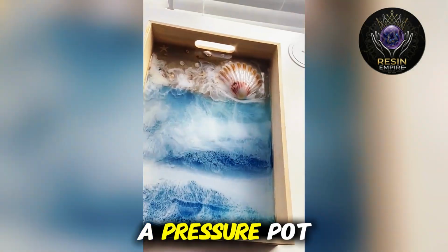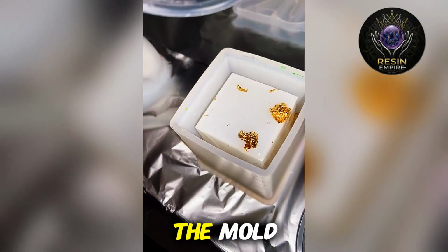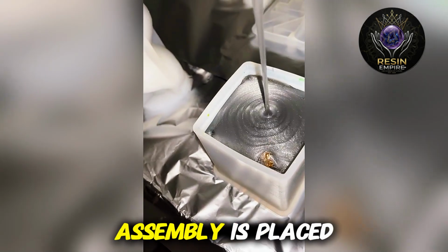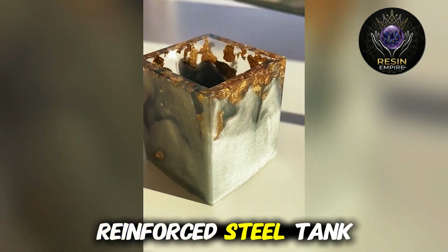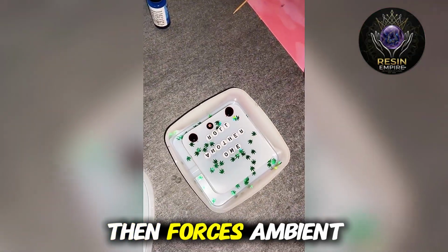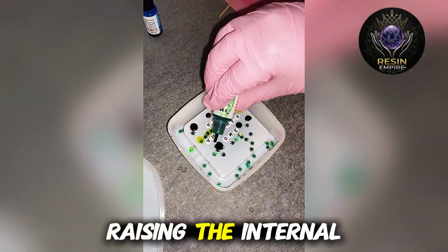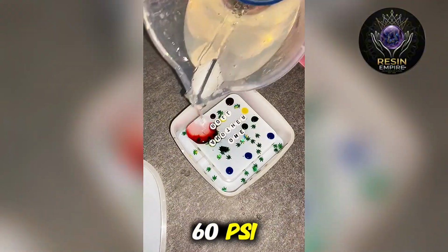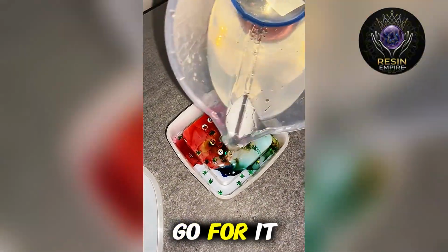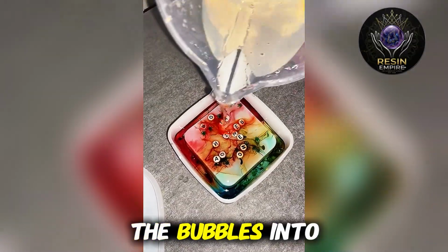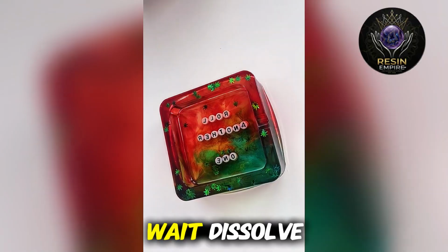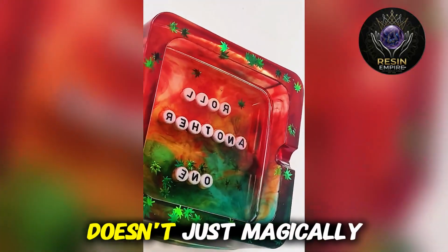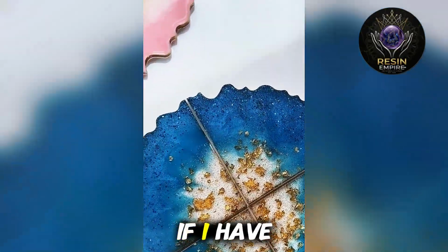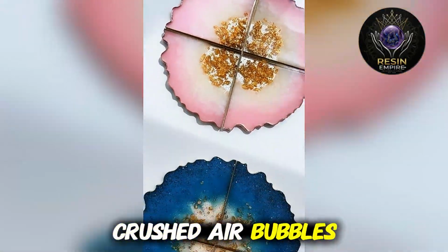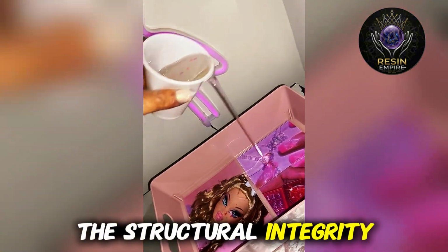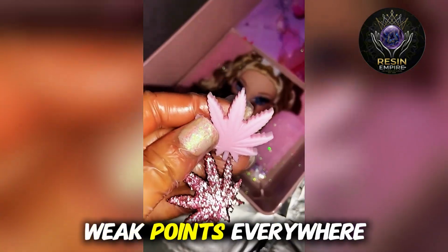Precisely opposite, yes. A pressure pot is utilized after the resin is poured into the mold. Okay, so the mold goes in. The entire mold assembly is placed inside a heavy-duty reinforced steel tank. An industrial air compressor then forces ambient air into the sealed tank, raising the internal atmospheric pressure to around 50 or 60 psi. And this is where I need to challenge the physics a bit. Go for it. The sources say the pressure pot dissolves the bubbles into the resin matrix. Wait, dissolve. The atmospheric gas doesn't just magically disappear from existence. If I have a piece of plastic with millions of crushed air bubbles hiding inside it, does that change the structural integrity of the piece? Are there microscopic weak points everywhere?